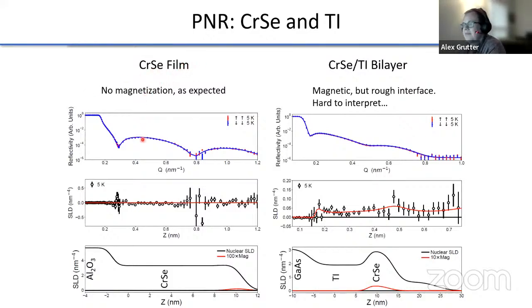So now we're talking about an antiferromagnetic proximity effect, where we count on the spin polarization of the chromium spins at the surface to induce a magnetic moment in the topological insulator. We can test that it is in fact antiferromagnetic. Neutron reflectometry of a pure chromium selenide film shows basically no magnetization, like you'd expect. But as soon as you grow a chromium selenide layer on top of a topological insulator, all of a sudden you have a spin asymmetry popping up right here. This gives you a magnetization that appears to be relatively close to the interface, but it might be biased toward the chromium selenide layer.